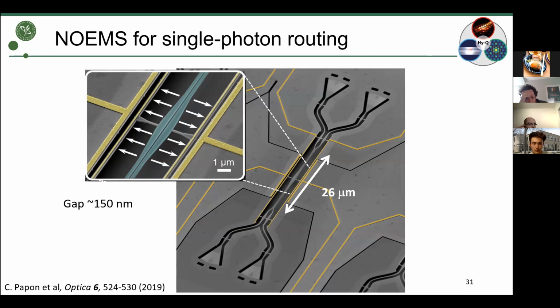But if you have strong electric fields on a semiconductor, you can have electroabsorption, so basically you're making the material more absorptive than what it is, especially close to the material band gap. And since we're not that far, this is potentially an annoying problem. But we have not seen this here because indeed the fields are really far away. They're decoupled from the optical region. Thank you.